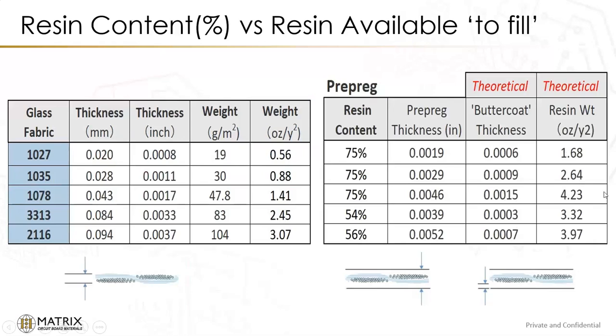Hey, Rick. Go ahead. Yeah, Bob Jaff here. You can put in at least almost 2.5 times as many plies of the thinner material. So even though it doesn't have as much butter coat, you end up with more fill resin per mil of total thickness with a lighter cloth. Yes, we'll get to that. I've got some slides on that too.